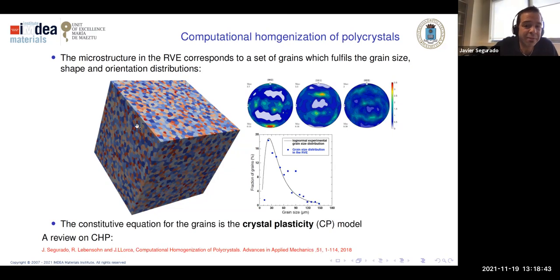And what you have on the left is, if we take this information, and we know how equiaxial the grains are, we can build this type of representative volume element. This is a very huge RVE that contains tens of thousands of grains, but it's something that is doable within FFT.